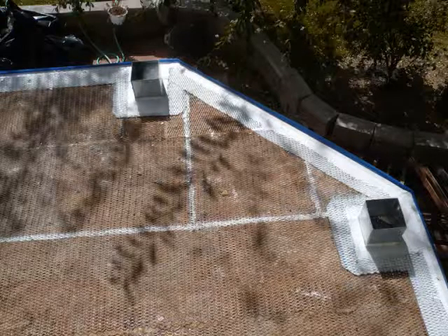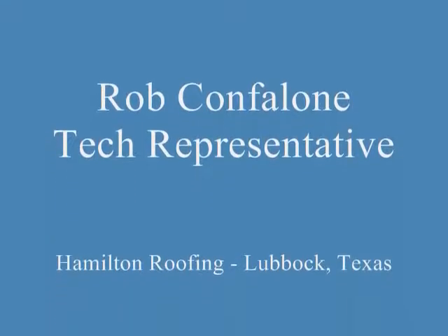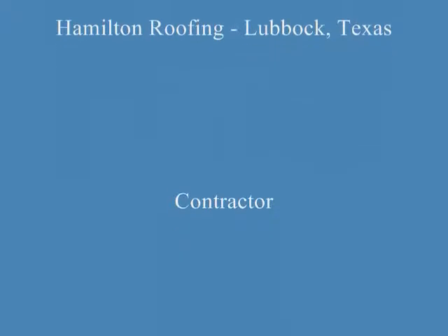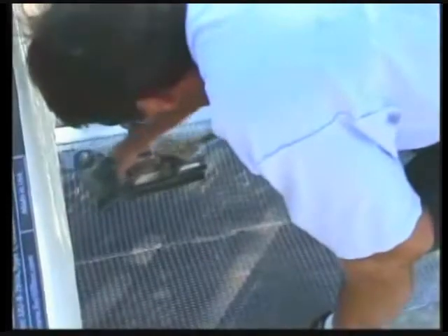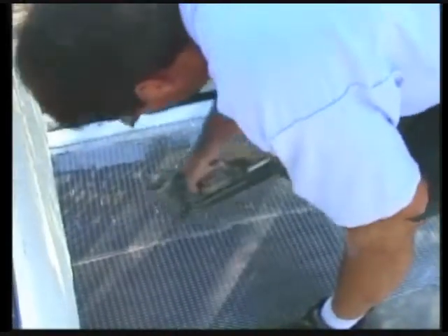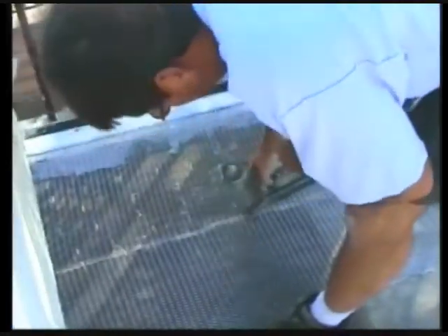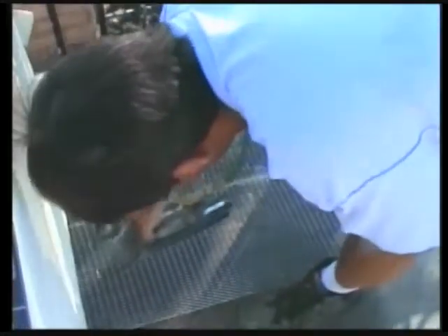We will now move to the installation of the metal lath and deck coating section of the Flexideck PML system. Here the contractor is installing the metal lath by stapling it down with 2-inch staples, approximately 20 per square foot. The metal lath is butted to each other and not overlapped. The sand slurry will begin to be mixed and applied to the metal lath in the next step.